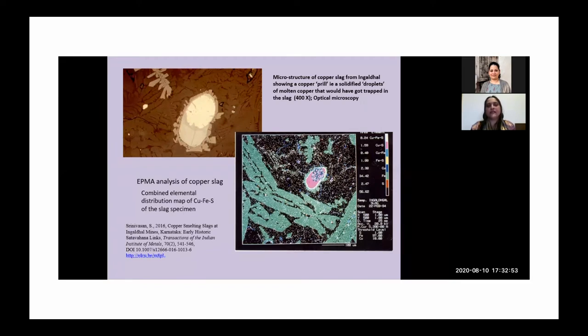Because for instance, in this case, it's quite interesting because the sulfide ring tells you that this is not actually the smelting of copper oxide ores, but it's already the smelting of copper sulfide ores, because you see this ring of sulfide which is formed around the copper prill. And so in this case, it's a chalcopyrite ore, and that tends to also have a lot of iron impurities. And so the iron gets into the glassy matrix to form fayalite and so on. And so what you're seeing in the center there is the prill of copper metal.